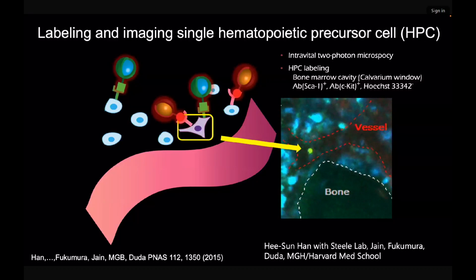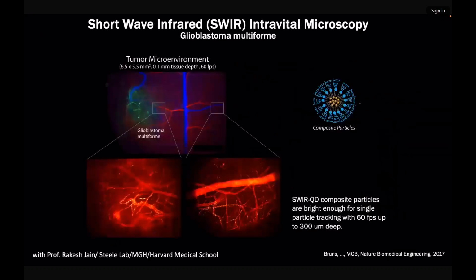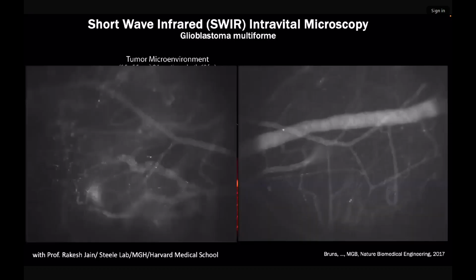The other thing that we were able to show is that quantum dots and light dye molecules can go into the infrared. And the infrared is less scattering. We were able to make these composite nanoparticles that emit in the shortwave infrared. This is a glioblastoma model. And you can then go look at these single composite particles and track them in time. They're big enough you could see single ones. And then you can see the difference in flow between healthy tissue and diseased tissue.